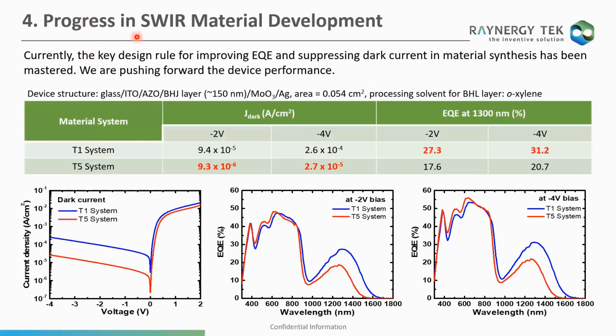Now, regarding the progress in SWIR, you may be curious, can organic material be stable enough for such a small band gap? Yes, we can. We're slowly getting there. We started from zero early last year. Now we are making progress to meet a customer target, which is QE at 30% and dark current at less than micron level. So now what we have is a T1 system where we register at -4V. It's with 31%, which already achieves the customer spec, but we still need some tweaking to lower down the dark currents. And the T5 system shows extremely good dark currents, but we're working on the QE. So we are blending these two systems now to make it work for the customer.